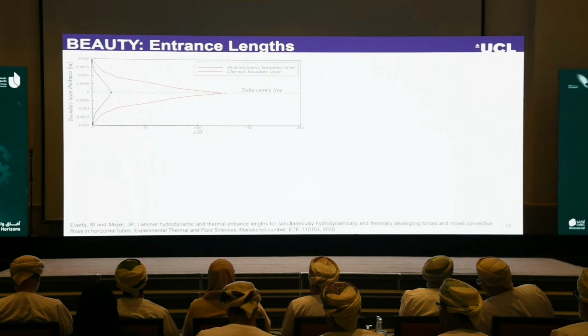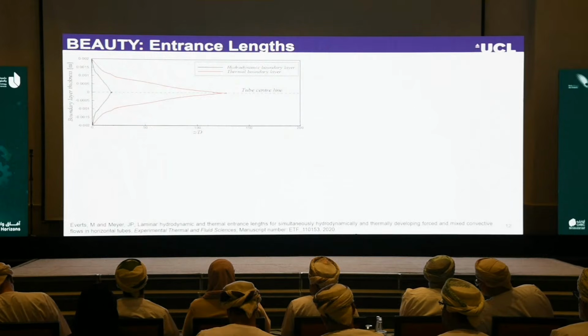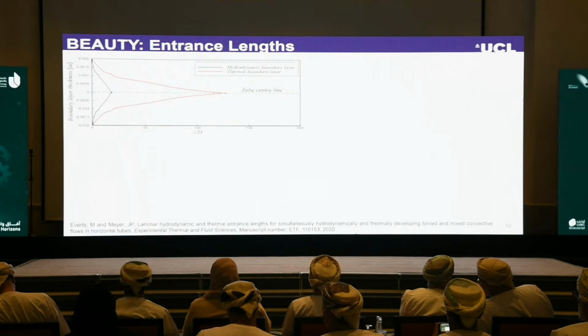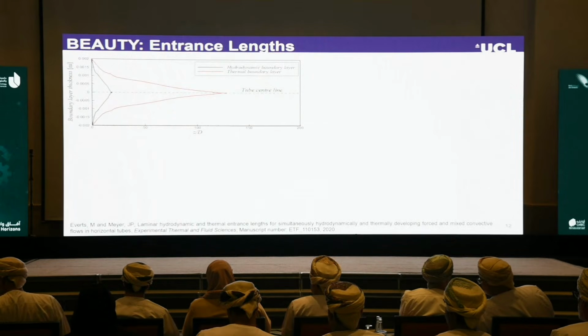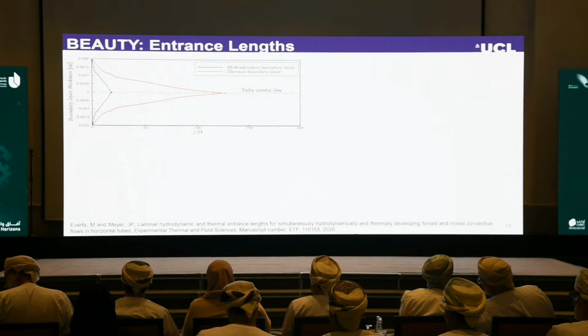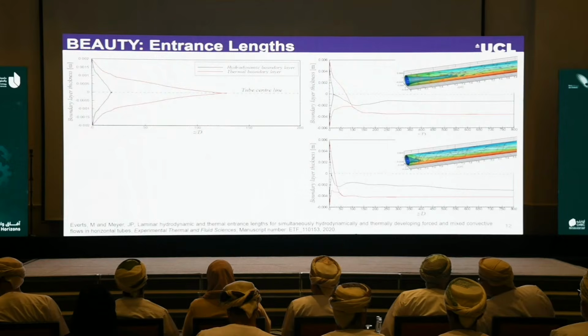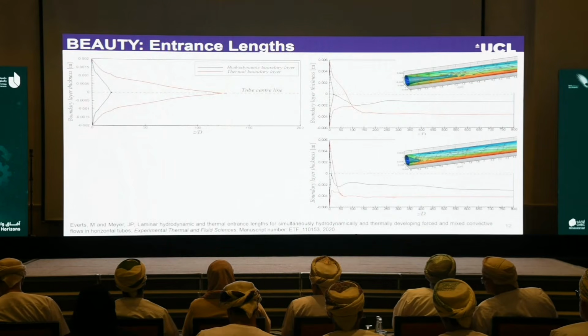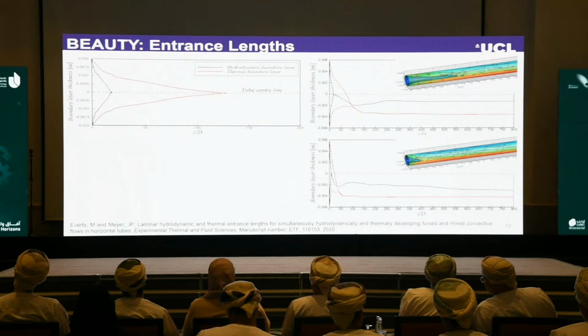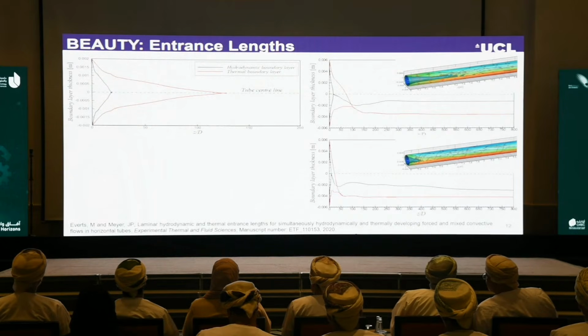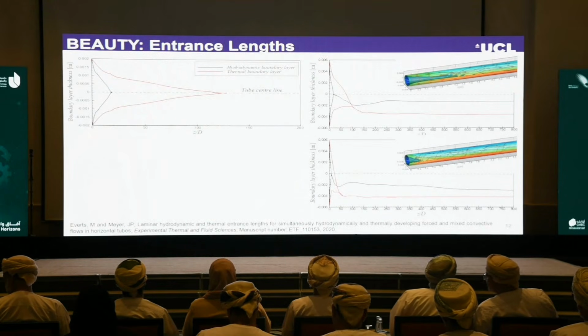So as a starting point, looking at forced convective flow, it was typically as we would expect from our textbooks. The black is the hydrodynamic boundary layer, the red is the thermal boundary layer. As the flow enters a heated tube, these two boundary layers start developing and they merge in the center of the tube. So that's good, confirmed, but now what happens for mixed convective flow? Here are two cases: the top is for a quite average mixed convective case, and the bottom graph is an order of magnitude higher mixed convective case. As we can see now, all of a sudden, what we've learned in textbooks is not really what we're dealing with in practice, and we need to better understand what's really happening inside our heat exchangers.